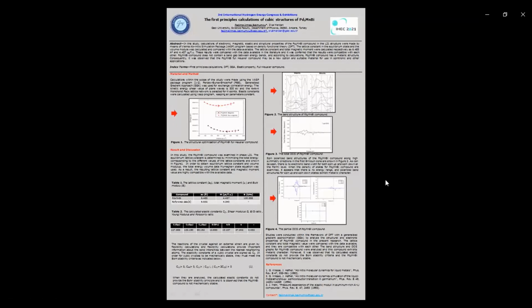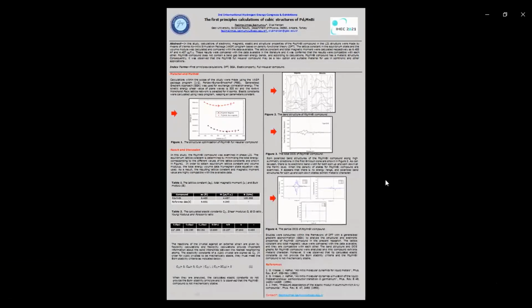Firstly, I will talk about material and method. Calculations within the scope of the study were made using the VASP program. The Perdew-Burke-Ernzerhof generalized gradient approach was used for exchange correlation energy. The kinetic energy cutoff value of the plane wave is 500 electron volts. Elastic constants were calculated using the VASP program, keeping all parameters constant.